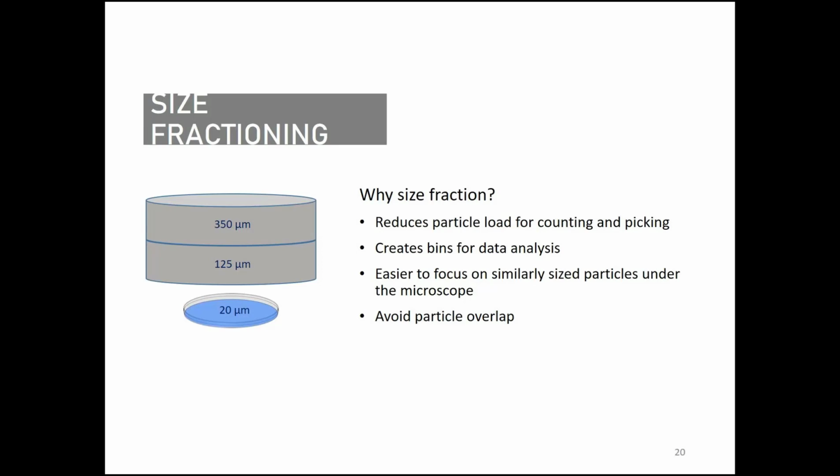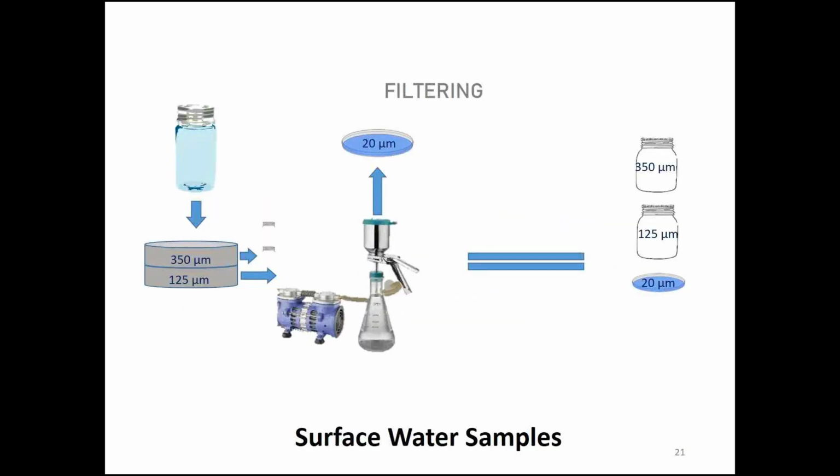Now if you go to the next slide, I'm just going to go through each of the different extraction protocols that we used. For surface water samples, this includes both Manta as well as 1 liter. We actually used a really simple procedure, which was just simply sieving and filtering to a smaller size range for the 1 liter sample. I know that some people use a wet peroxide oxidation for Manta sampling, and for some samples, especially in freshwater, we find that's really necessary.